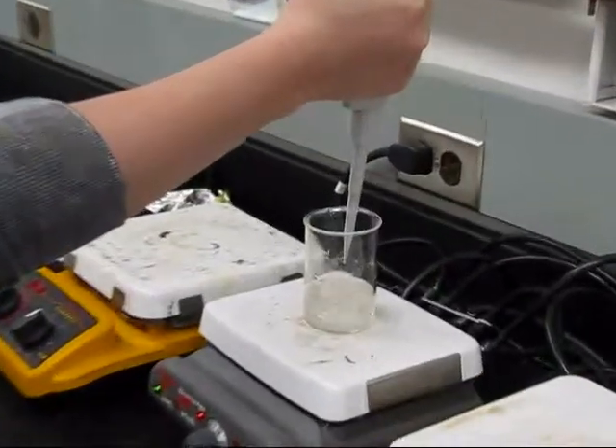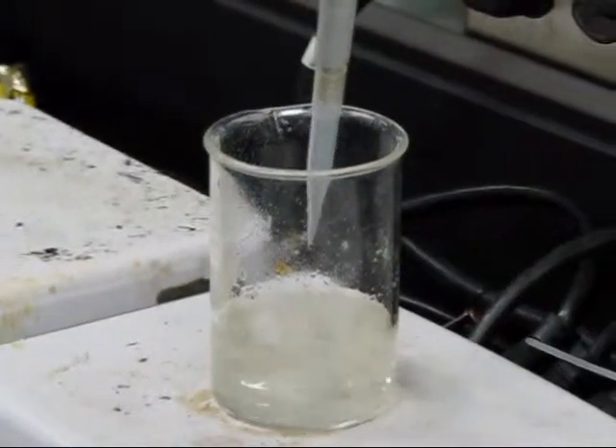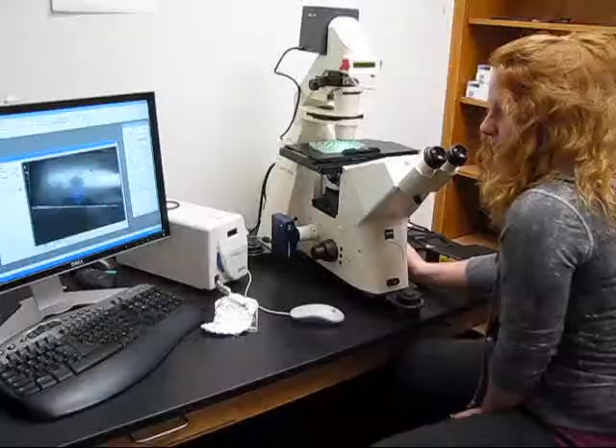What we want to do is coat the electrode in a Sol Gel, and hopefully that will reduce this inflammatory response if we encapsulate drugs in it or anything like that — basically find a way to eliminate this so we can have electrodes used over an extended period of time. What we worked on this semester is putting drugs into this Sol Gel coating and seeing if they can release over time. That seemed to work pretty well, so now I'm finishing up and making sure that the coating is crack-free and looks really nice.